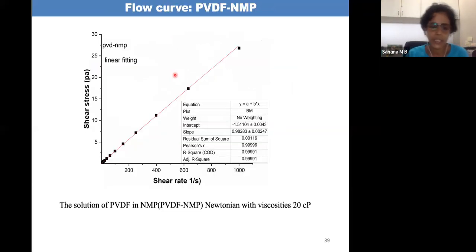Now, how do we study this? Let's say I described the process of slurry preparation. First, we mix the NMP with the PVDF, and then we see its rheological behavior. As we apply a shear rate, we can see that the shear stress keeps increasing. This behavior is called Newtonian behavior. These kinds of slurries will not sediment, since there are no solid particles here. It's a complete dissolution of PVDF in NMP.